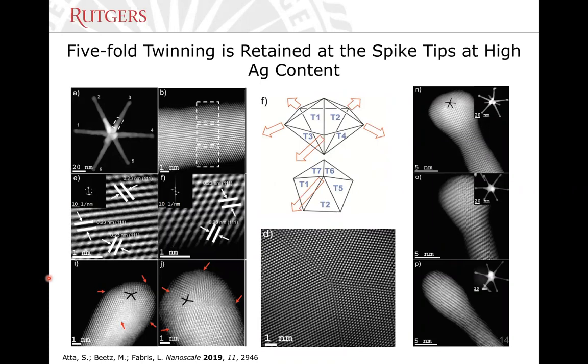So what we realized in this study is that starting from the spherical seed, that is a single crystalline seed, the key step that needs to occur to produce this nanostar is the evolution of the seed from a spherical single crystalline seed to a 5-fold twin seed that has a decahedral shape. So what we see here is this decahedral shape seed, 5-fold twins here, and the presence of silver nitrate and Triton X-100 is necessary for the particular growth because these two entities will adsorb selectively on selective positions or facets on the growing seed, leaving only the corners here, the 7 corners, available for growth. So that's where the 7 spikes come from. Obviously, as I said, there are going to be defects and this is something we have to deal with, but ideally that's what we should expect.